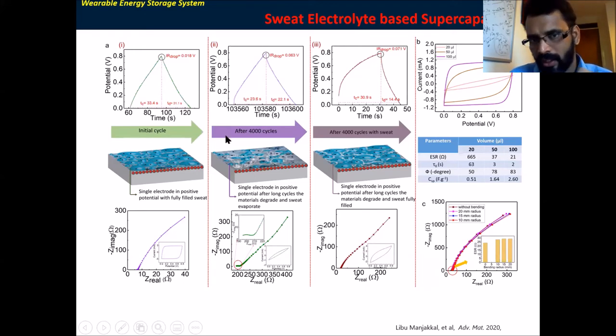Then after 4000 cycles, I measured again with continuous measurement. I noted that the charging and discharging time decreased and the resistance increased. So I opened my device and found that the electrolyte had evaporated, almost all the sweat. But after 4000 cycles, it was still showing some performance. That means a content of small ions is there that enhances our performance.